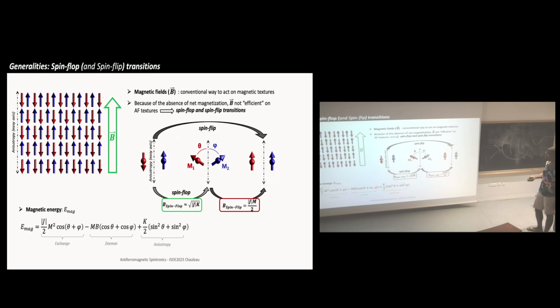Basically, anisotropy and exchange have to compete with the Zeeman energy, because let's say if you apply the magnetic field like this, this spin is very unhappy and this spin is kind of happy, so they try to find some kind of arrangement together. So then you go from the antiferromagnetic to a canted state. This is what we call the spin flop. And most of the time, the spin flop field scales as the square root of the exchange times the anisotropy.